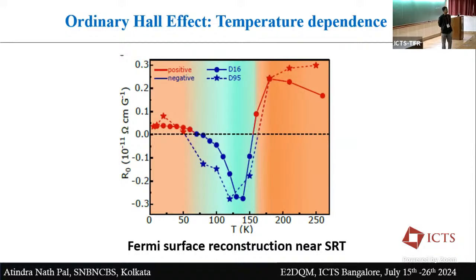If you plot the Hall data, from two devices we have plotted, we can see that this Hall data shows a very interesting transition. Initially it was positive, but near the spin reorientation it changes sign. But if you observe again, around 40 Kelvin, it again changes sign. So that means there is a Fermi surface reconstruction happening near the spin reorientation transition as well as at a lower temperature. So there are two kinds of transition happening in this material.